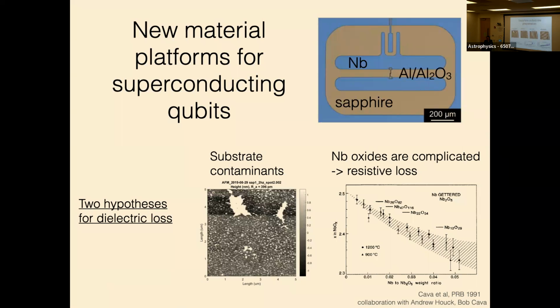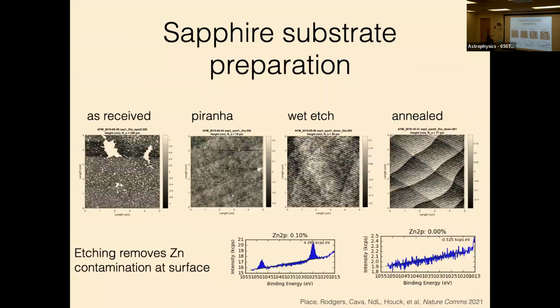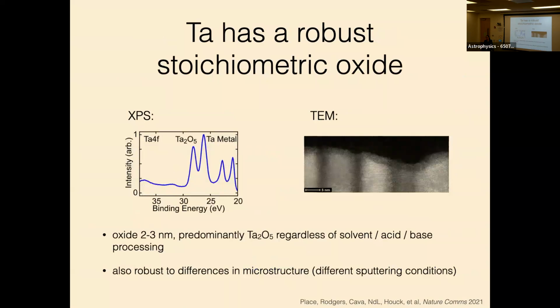Okay, so there are two lines of attack. The first was just, let's make these surfaces clean and smooth and contamination free. We worked a lot on sapphire substrate preparation. And then the second line of attack was, let's replace this niobium with something else that has a better looking oxide. So if you just go one down on the periodic table, tantalum, which is a refractory metal, is known to have a very nicely behaved oxide. It's a kinetically limited oxide where you always get 2 to 3 nanometers almost no matter what you do, similar to aluminum. And you always get the same stoichiometry. It's always Ta2O5. And the interesting thing is that this is really robust to processing and differences in microstructure. You just always get this 2 nanometer thick layer.